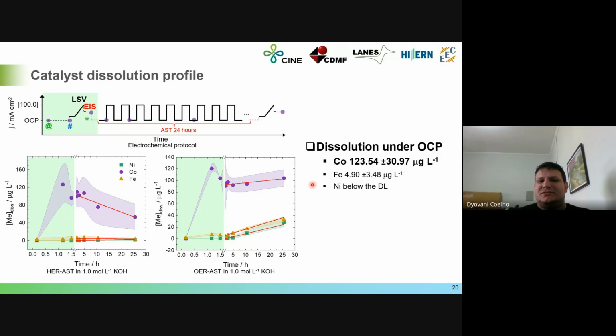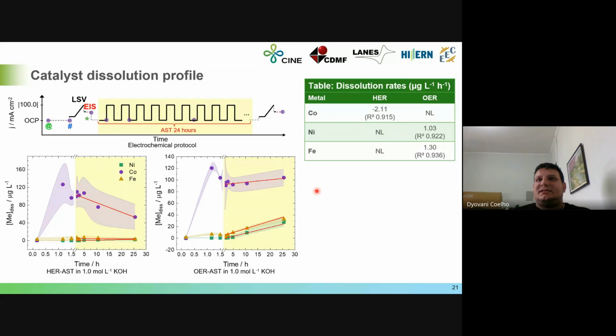Iron, we have just a little of iron from the catalyst, and this can be explained even by some kind of contamination, but not by catalyst degradation over time. But nickel is stable in this kind of condition. But this doesn't happen with cobalt. Cobalt is not stable at all during the open circuit potential. But during the accelerated stress test, the behavior changed a little.